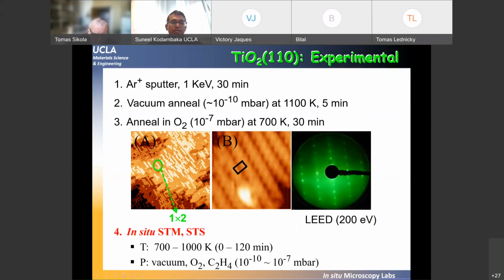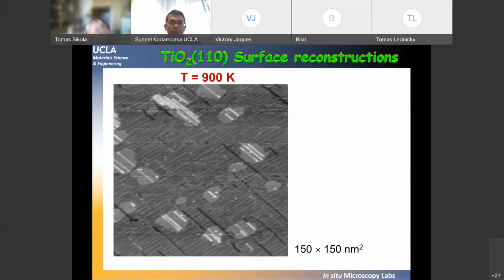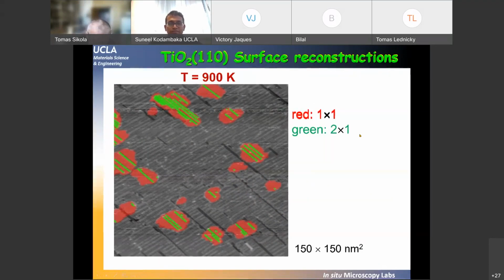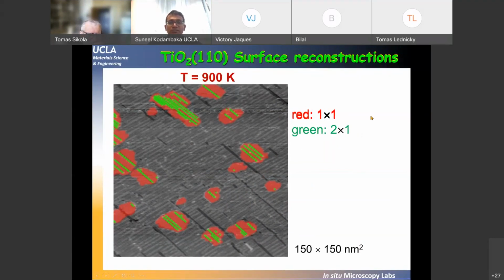And for TiO2, each of these stripes, once you have a complete layer of these stripes, you recover the 1x1 phase. And again, it repeats itself. So these underlying layers, let me show it to you on the next slide. So here you see the TiO2 surface, and this is a scanning tunneling microscopy image that's obtained while annealing in vacuum at about 900 Kelvin. You see these relatively flat, slightly grayish color islands. These are 1x1 phase. And on top of these 1x1 phase, you have these stripes, and these are the 2x1 phase. And once you have enough 2x1 stripes, you recover the 1x1 surface again.